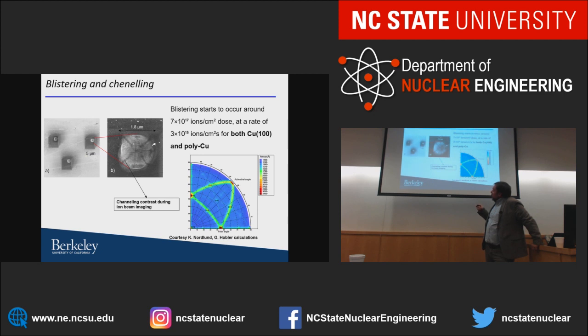Interestingly, the black lines we think is actually ion channeling, because when you shoot the ions in at specific crystallographic directions, the ion travels deeper in the material than it would in others. And so when the ion travels deeper, since the image you're creating is a secondary electron image, you have less signal to your detector, therefore it's dark. And so if you happen to hit the channeling axes, then you get a black line.